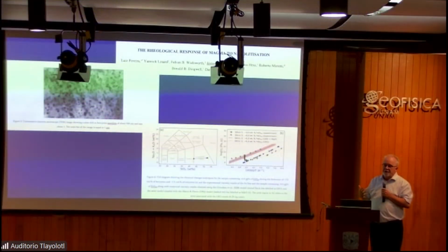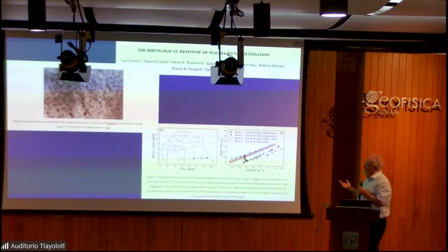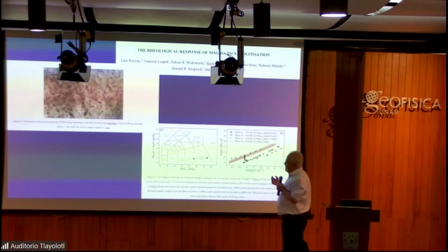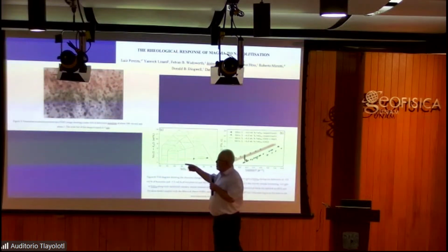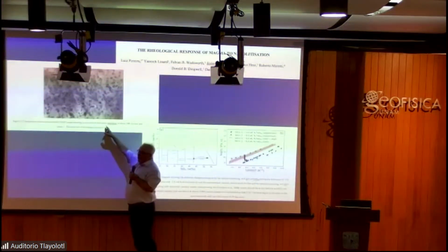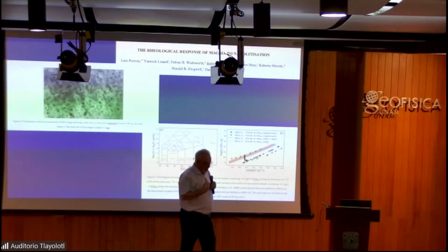Now, in recent years, other scientists have come up with the idea that nanolite crystallization, which we believe can occur during the eruption, may suddenly switch the viscosity in the system, because if you have enough of it, it may have a physical influence on the viscosity of the system as a suspension of nanolites. The prime candidate is usually an iron-bearing phase. In this case, it's a hercynite, that's a spinel phase, right? Iron and aluminum. But we also have studies with iron oxides.